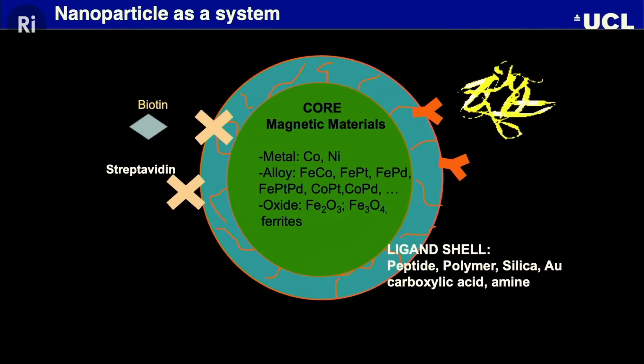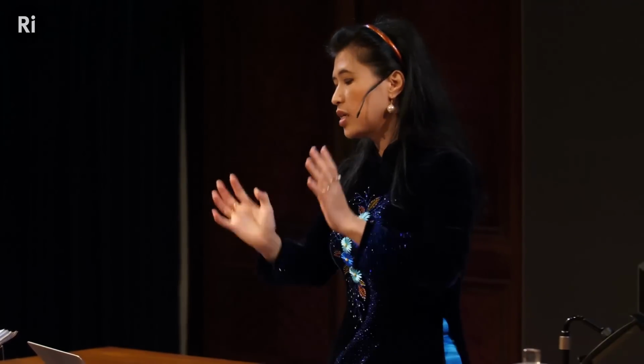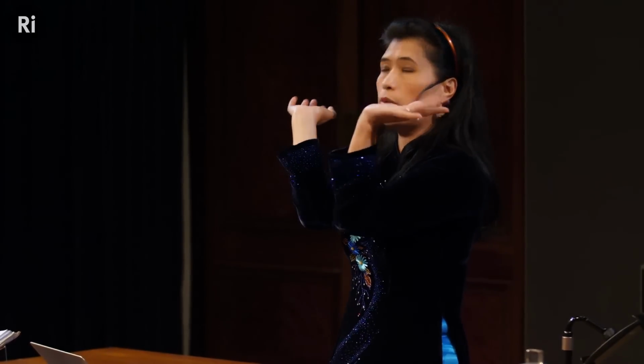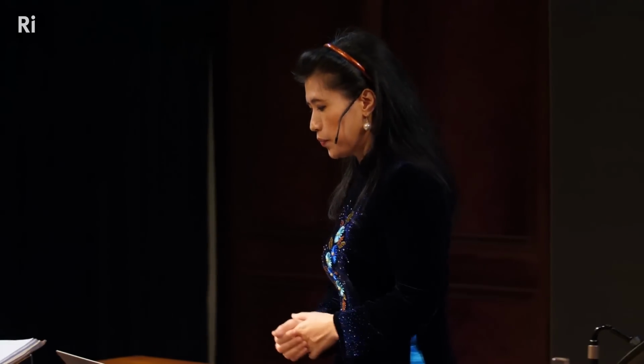So when you think about the nanoparticle, you need to think of it as a system, because you've got the core. The core can be magnetic, plasmonic, or of different chemical composition, but you need the shell. The shell here is really, really important. Why? Because when you inject this nanoparticle inside the body, your body is not seeing the core, it's seeing the shell. So the shell is really important for how they are going to behave. And if you want to have some interaction, you will have something specific. I'm just giving you a very small example here, like the immunoassay, antibody and antigen. You need to have a particle with this antibody, and it is going to interact with the antigen. So you have this specific entity doing the job of the interaction, okay?